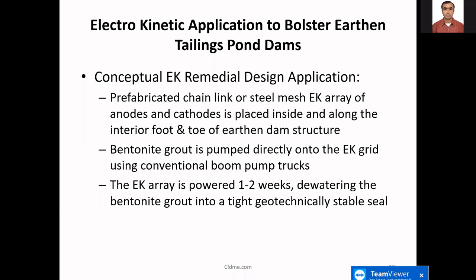And the EK array is powered for 1 to 2 weeks. In my experience doing most of the testing at the lab here at UIC, it was typically about a week. We saw as much treatment as was necessary. And also most of the water moisture content was down below 60%, which is the secondary goal for the treatment.